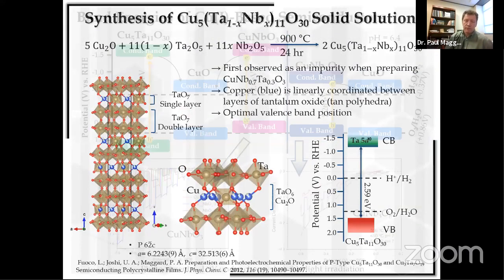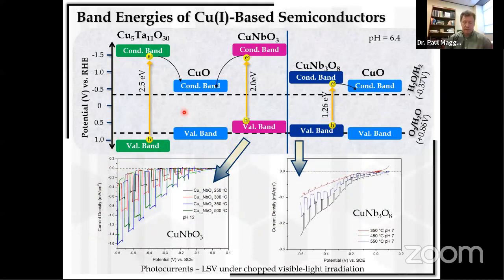Now, I must go back here and make one further comment. And the comment is that copper oxide systems, especially 1+, are relatively unstable in solution. So these will photodegrade over time. And many other groups have looked at how you put protecting layers on their surfaces to make them highly stable and to maintain a very high efficiency. And this really hasn't been a direction that we've pursued in my group because of other competing groups that are pushing this direction very well.